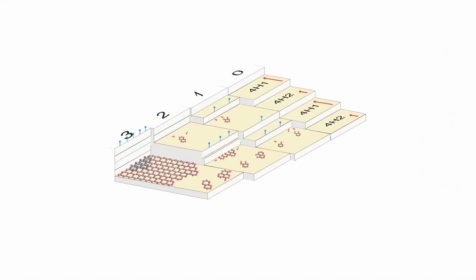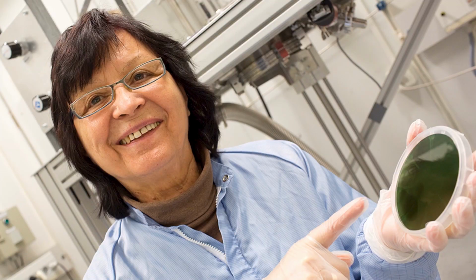But from the beginning, it was a graphitization which was not good for the growth. And there we can come back to this step flow growth and step bunching which appears on the silicon carbide and also some other materials, to understand more how we can form monolayer over a larger area intentionally and so on. So we explored this a lot. And now we can do this in a wafer size. So here my supervisor from that time, Rositsa Yakimova. She initiated this research and she was supervisor for me there, and we still collaborate on the silicon carbide and related growth activities.